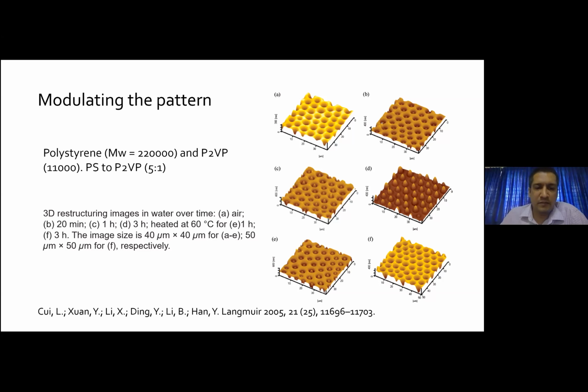And once the breath figure is made, the first one is the as-prepared breath figure. Then what they have done is they exposed this patterned surface to solvent. For example, if you expose it to ethyl alcohol, the ethyl alcohol tries to swell the poly(2-vinylpyridine) to a larger extent compared to polystyrene. Polystyrene is not soluble in ethyl alcohol. So in that case, the poly(2-vinylpyridine) swells. It doesn't dissolve, it swells in the ethyl alcohol.